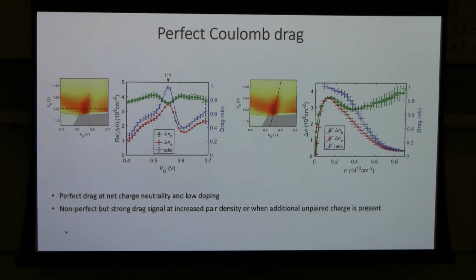Similarly, we can go along this charge neutral line. That means we have only excitons in the system, but with more and more exciton density. We find that at low density of excitons, the drag is close to 1, but at higher density, the drag actually becomes smaller. So maybe it is because a lot of excitons start to get dissociated.